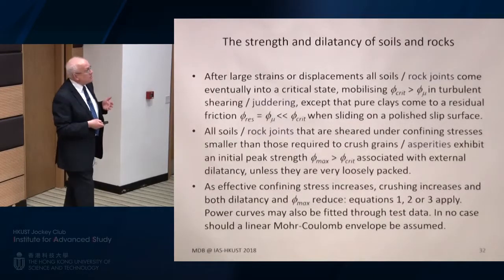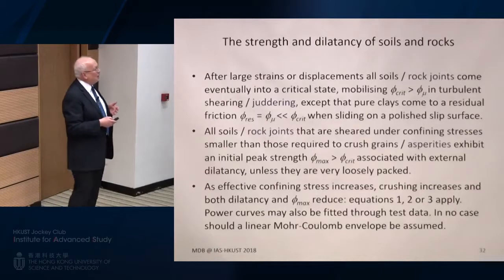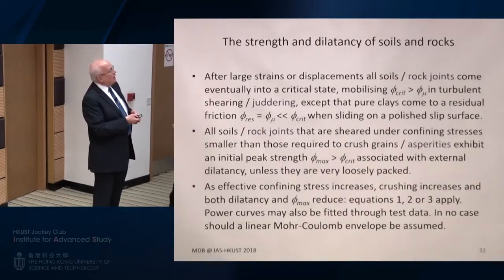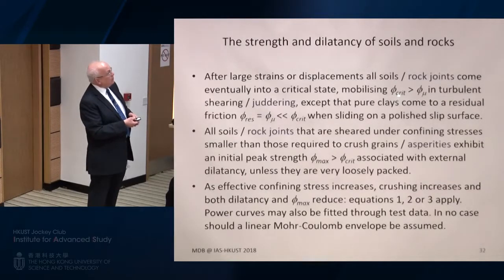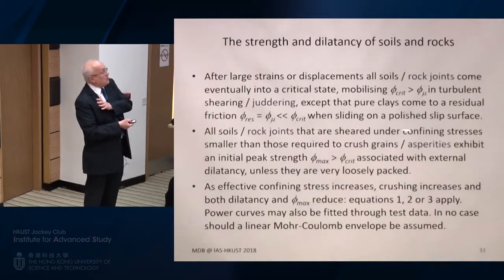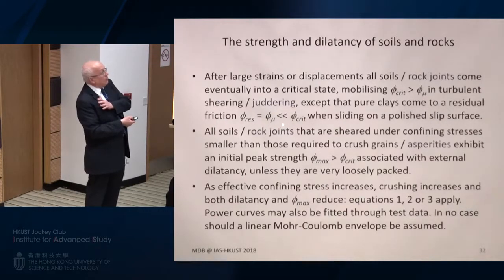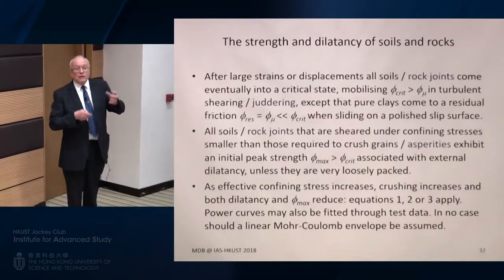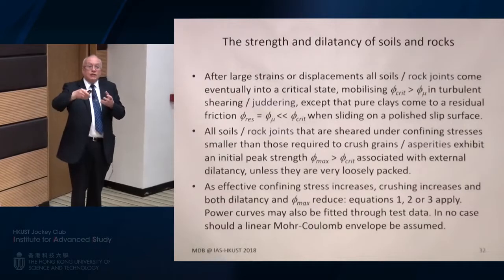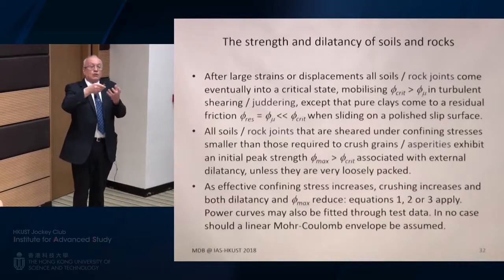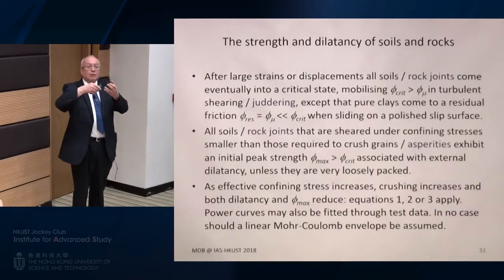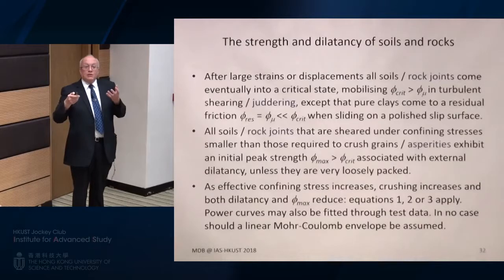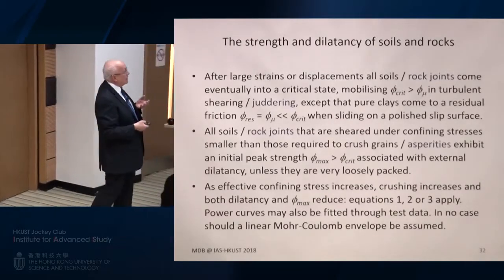So strength and dilatancy of granular geomaterials is all of a piece. You get at large displacements, large strains, phi crit greater than phi mu, except for polished slip surfaces where you get what we call a residual phi, which is probably the same thing as a phi mu, which obviously is much less than phi crit because of the interlocking, juddery nature, the internal strong force network being undemocratic in how it distributes stresses inside the granular material.